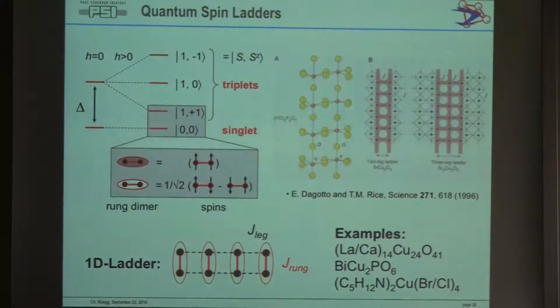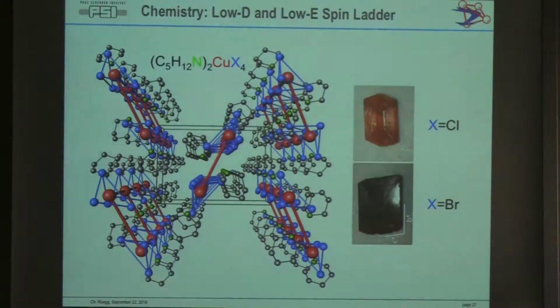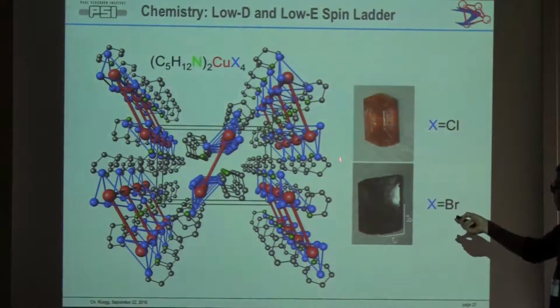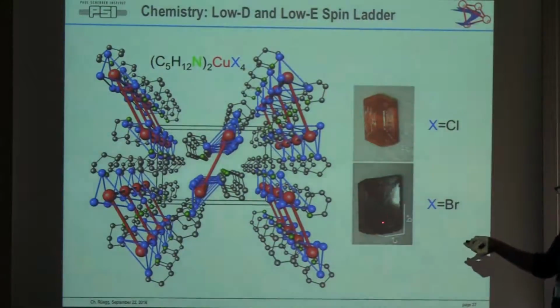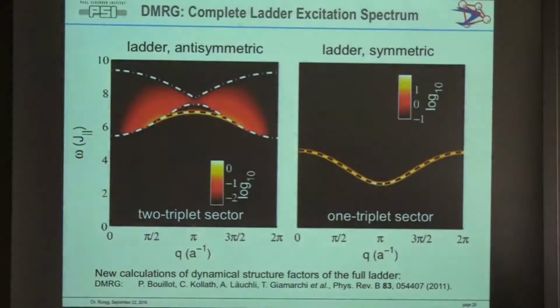And I will show you now about these metal organic materials. Basically, these are a very good realization of these Hamiltonians at a very low energy scale, which is very good for field tuning. So there's actually 2 versions. You can have a chloride and a bromide. Bromide usually has an exchange which is roughly a factor of 2 larger than this. And from this slide with a periodic table, you would expect something like a milli-electron-volt or a few milli-electron-volt of exchange parameters. And that's very good because even here, you already have 2 different materials. So if you want to have something which has a bit lower gap, you just take the chloride. If you want a larger gap, you take the bromide. So there's some flexibility in that. Both have the same structure.